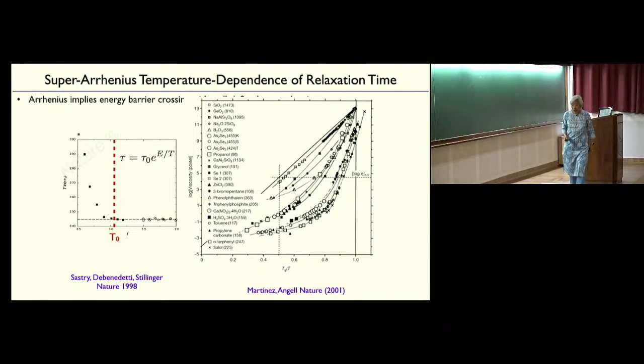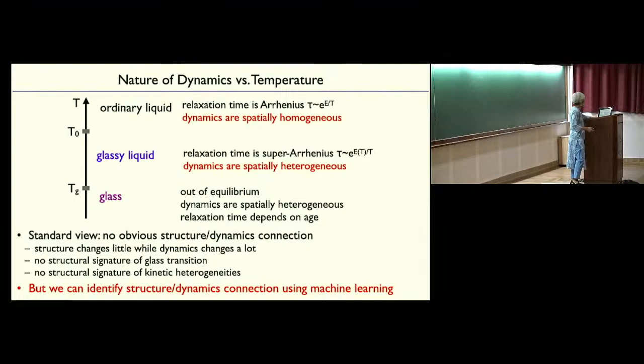It was discovered by Srikanth Sastry back in 1998 that for these fragile liquids, the ones with this sort of behavior, if you look at the effective energy barrier, it's flat above a certain temperature. So there's this well-defined energy barrier. That's why you see Boltzmann-like dependence. But below this onset temperature, it shoots up, so the effective energy barrier depends on temperature. The energy barriers get higher as you lower the temperature. And the cool thing is that it happens at a characteristic temperature, which is the onset temperature.